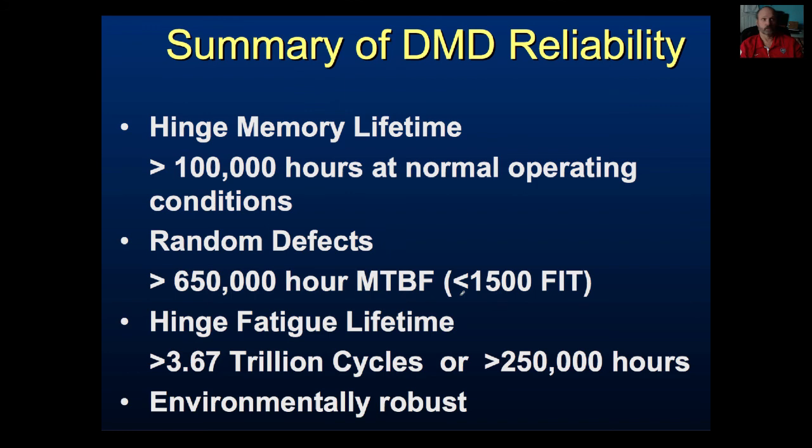But then they got to the point where 96 to 98% of the chips worked, which means that 100% of the mirrors worked on those chips. So you can do the math. That's really hard to do. Make a few million devices and they all work, right? And they're all part of one package. So you get an idea. The hinge fatigue lifetime was greater than 3.67 trillion cycles, or 250,000 hours of use. And it was robust in the environment. So they actually would seal these chips off with a glass plate.